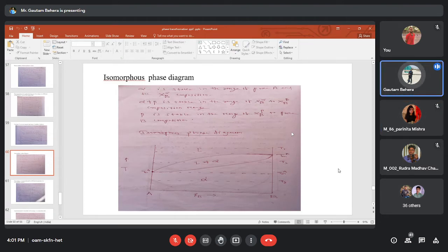So that means you can take two components, for example, copper and nickel. You mix them, the copper and nickel will be 100% soluble in the liquid phase, as well as soluble in the solid state also. So there is 100% solubility in liquid and solid state, right? Okay. And any other example, anybody remember? Any isomorphous phase system? Gold and silver. That's why silver is added to gold, sometimes, to make it 22 karat or maybe 20 karat. It depends how much silver is present in gold. So silver and gold are also an isomorphous phase system, right?